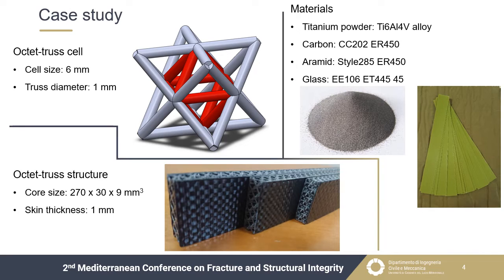The characteristics of the lattice core are very important since they influence the mechanical peculiarities of the whole structure. As concerns the cell type, the octet truss lattice was chosen. This cell is a face centered cubic cell, formed by 12 struts that in the figures are represented in gray color, with an octahedron inside, highlighted in red color. After several tests aimed at evaluating the possibility of removing the unmelted powder from the lattice, the cell side was chosen equal to 6 mm, while the truss diameter to 1 mm.